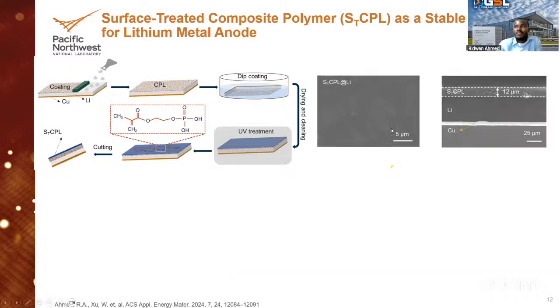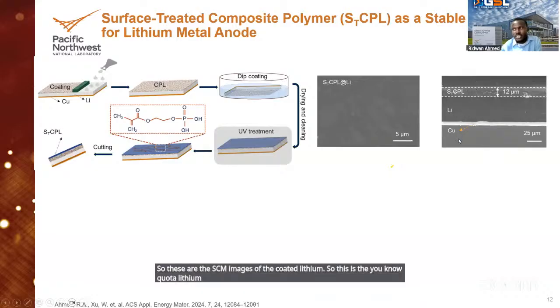So these are the SEM images of the coated lithium. So this is the coated lithium, and this is the cross-sectional image. This is the copper, which is the current collector.